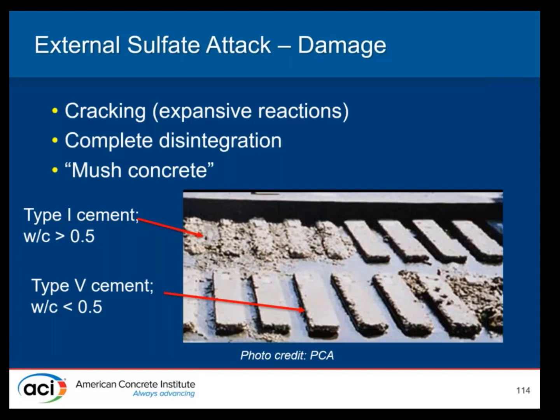Those are 6 by 6 by 30-inch beams that were used in a sulfate exposure test plot in Sacramento, California. The specimens were designed with different water cement ratios, different types of cement, and exposed for 6 to 7 years to sulfate saturated medium. So basically they were wetted and dried, with the wetter and drier being a high sulfate solution.